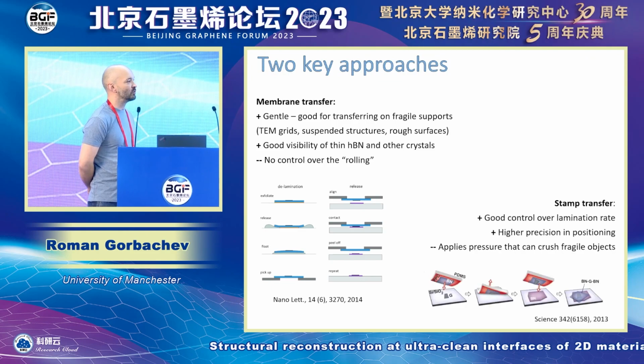Today, there are two key techniques. One of them is using very thin membranes of typically PMMA polymer, and the other one is called stamping, and it's using PDMS with another polymer liner on top.